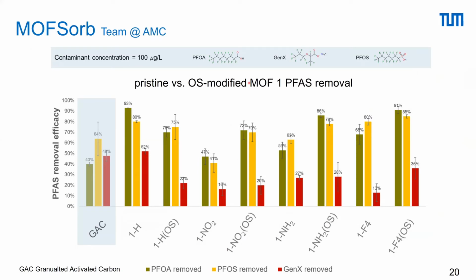And hot off the laboratory, this slide is shown to give you at least a taste. We cannot disclose too much about the nature of MOF1 for reasons which are probably obvious. So if you look at this first entry here, this is the granulated activated carbon, and the color code green, yellow, and red are three different fluorinated pollutants which need to be removed. And if you look at, for example, 1H or this 1F4OS, then you see that this one and this one clearly beats the granulated activated carbon. There is, of course, a variation of the selectivities and the retention or removal efficiencies depending on the MOF type and depending on whether we modified it or not.